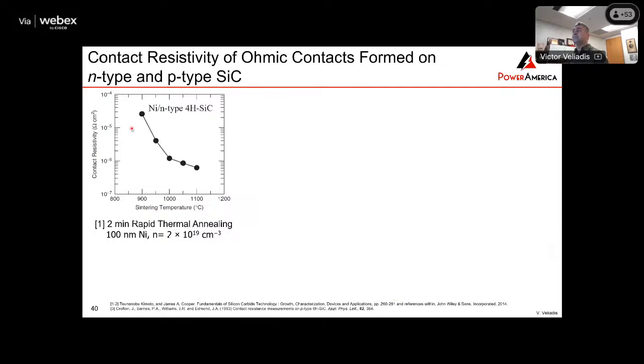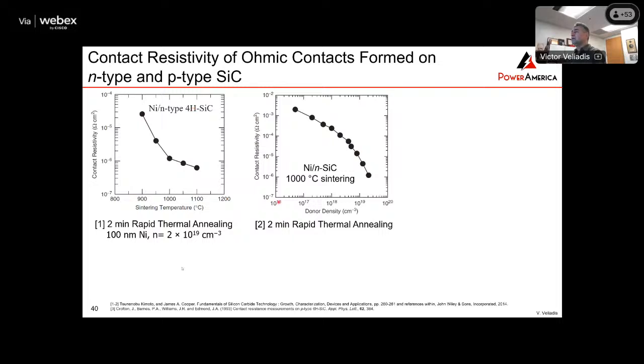So let's look at some of the things I mentioned before. If you look at this graph here, it shows the resistivity as a function of the anneal temperature, and you can see if you don't anneal, or if you anneal at 900 degrees, the resistivity is relatively high. By the time you get to 1,000 degrees and a little more, your resistivity goes down, and this is for nickel to form an ohmic contact on the n-type surface.